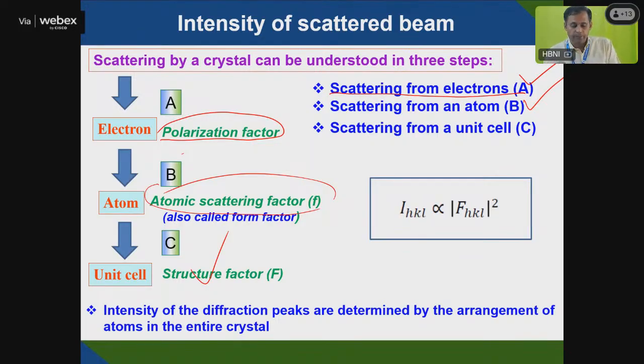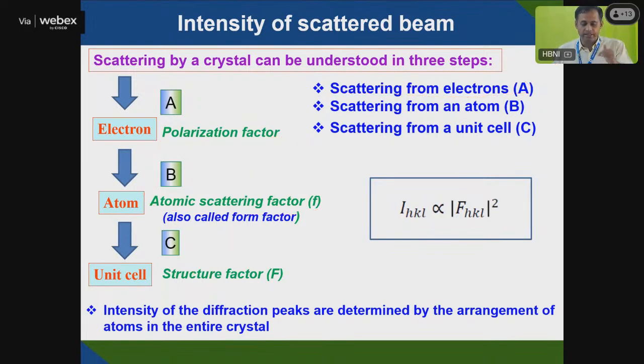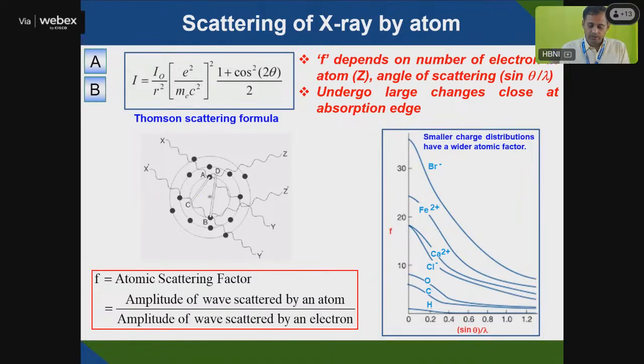So the intensity of an HKL plane, a particular plane, is proportional to the structure factor of that HKL plane. That means it depends on how atoms are arranged in a particular crystal structure, whether the atoms are FCC arranged, whether BCC, whether HCP. So depending upon the atomic arrangement, you are able to get the intensity. The scattering from an electron is mainly proportional to 1 plus cos square 2 theta, that is the polarization factor.